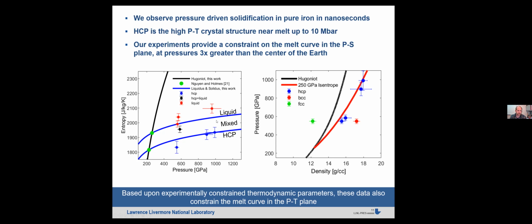So then what we did was we fit the melting curve, we fit both the liquidus and the solidus, assuming a constant entropy of melting, which is reasonable based on the statistics of melting. And we also force the liquidus and solidus to go through the pressures of incipient and complete melting. And so from this, we can obtain the melting curve of iron in the pressure entropy plane from 250 up to 1000 GPa. And we actually have a pretty tight constraint on that.